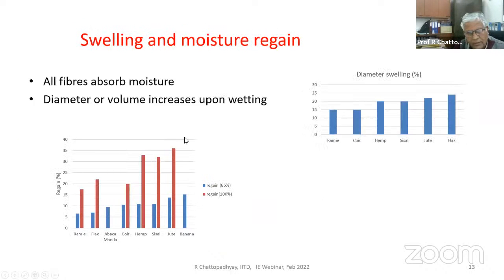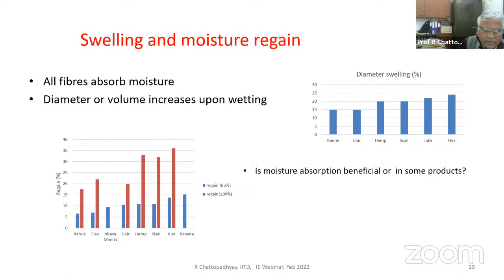Similarly, swelling and moisture regain. Most of these fibers will absorb moisture. And as a result of that, the diameter or the volume can increase on wetting. Now, this increasing diameter or volume could be beneficial in some products. So if we know how much swelling is possible in the different forms, in a single isolated fiber form, or in a group form, like in a yarn or in a fabric, then probably we can say that the swelling can be used as an advantage in some products, and in some products, this may not be that advantageous. So keeping this in mind, we can think of the use of these fibers.